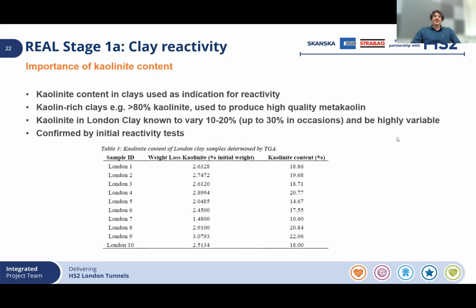To give a little bit of context, kaolinite content in clays is used as an indication for reactivity. 80% kaolinite and above is deemed very high quality clay to produce metakaolin, and we already know from literature that London clay varies between 10 and 20% kaolinite content, or even up to 30% on occasion, and it's highly variable. This was confirmed from initial kaolinite tests on raw clay samples, as you see from the kaolinite content percentage column, approximately 22%. Next slide, please.